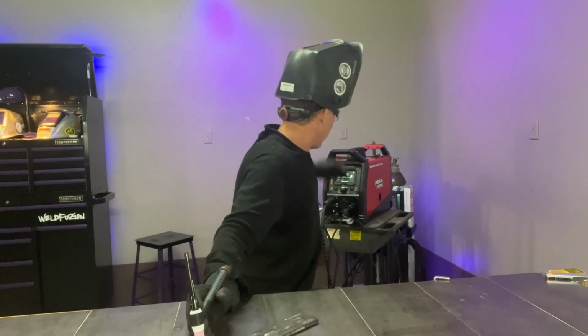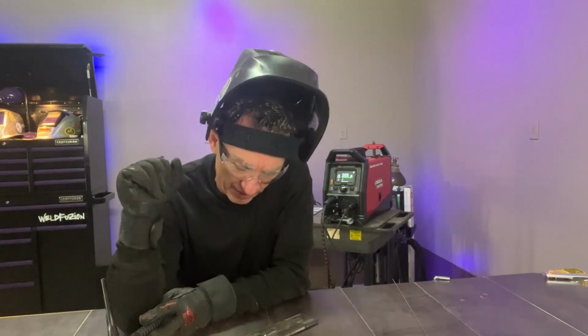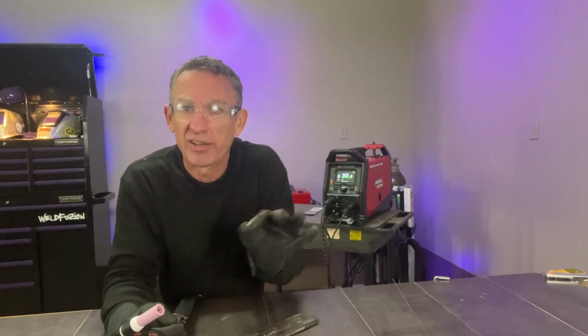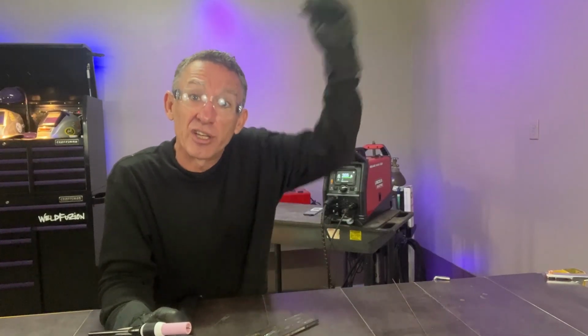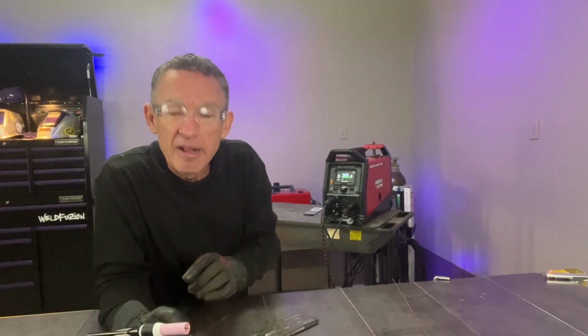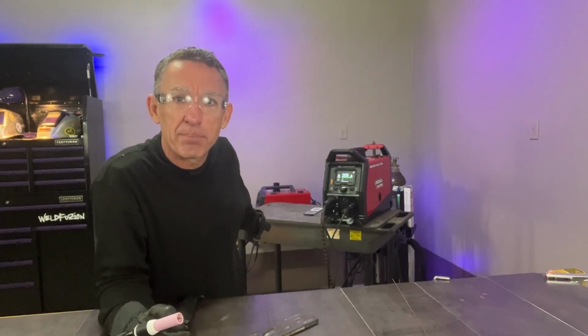Whew. I don't know what I'm cratering out to right there, but when I back down at the end of the weld and get right down to a really fine arc, it is stable. This thing is impressive. The arc start is super smooth. It's responsive as soon as I hit the foot pedal. I've got that nice arc start. You can tell that the arc start doesn't have a significant amount of amperage overshoot because it starts very, very soft. It didn't stumble once, and my shop machine is a